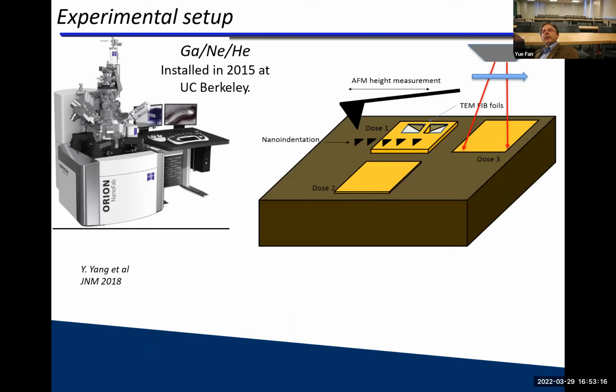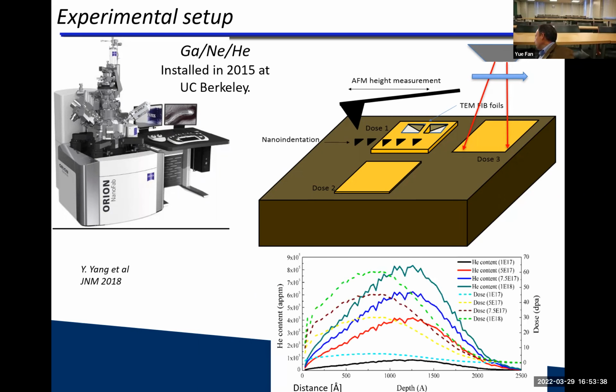You scan, you raster like an FIB or like an SEM, and then you have the same grain in the same region, and you watch swelling with AFM, you do nanoindentation, watch the hardness, you do TEM, and get all that out of a 10 by 10 micron region. Very effective to get many doses in the exact same sample. This is what the dose profile looks like if you do 25 keV helium, like in this instance, not of course accounting for diffusion. Diffusion smoothens that out some more.